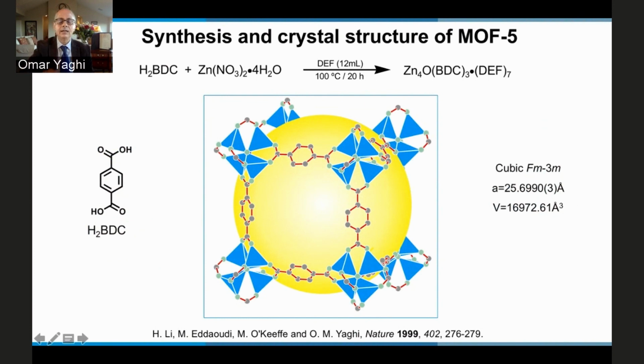The key development here is that we figured out the reaction conditions under which to crystallize this structure, which is entirely linked by strong bonds: carbon-carbon bonds, carbon-oxygen bonds, and oxygen, or one can say negatively charged oxygen oxide, and metal ion, in this case zinc, to make this extended structure. And we use the yellow ball to indicate the space within which other molecules can go in. So the synthetic conditions that you see here are still in use today in making carboxylate-based MOFs, with slight variations here and there.